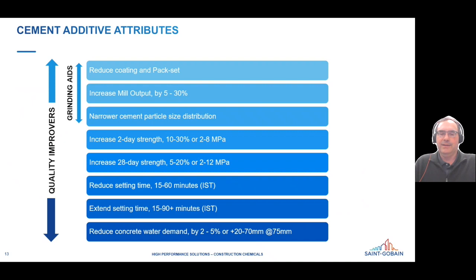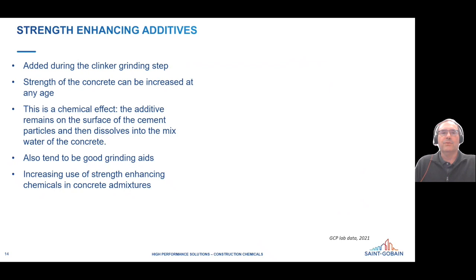So quality improvers are doing sort of both things. They're helping with the grinding process, and then they're also improving the properties of the concrete. And so what I'd like to focus on here with quality improvers is the strength enhancement attribute, which I think is the most important one. So strength-enhancing additives, again, are added during the grinding step, and these chemicals remain on the surface of the cement particles, and then when you go to make concrete, they redissolve out into the mixing water, and they have a chemical effect that actually enhances the hydration process and changes the hydration process.